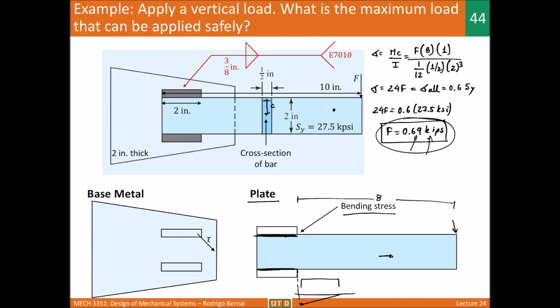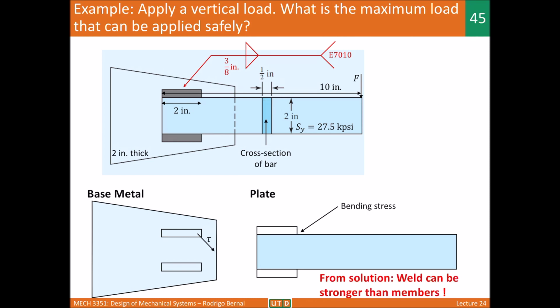Another lesson that you can draw from here is that actually the weld was more resistant than the individual members, the base metal and the plate. What we found is that to remain within safe limits for the stress, we could actually apply a higher force and the weld would not suffer, but the base metal and the plate would. And so that gives you sort of a lesson that applies for many types of welding joints, where the weld actually ends up being stronger than the members.